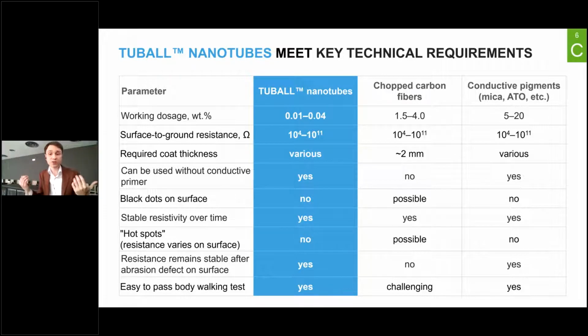In our case, you don't need to do it. We provide a very homogeneous conductivity in all dimensions, so you just need to make some small abrasion processing to increase the active surface and apply the same paint you were applying in the beginning. You don't need to cut the top layer.